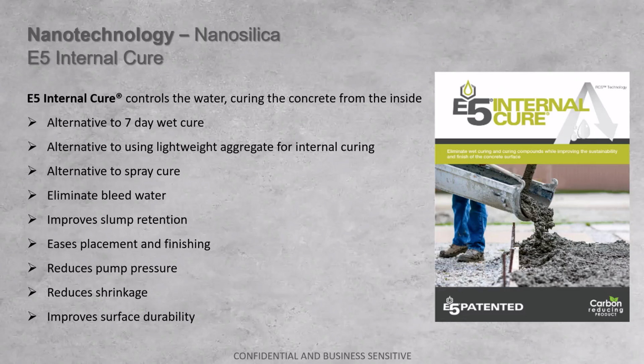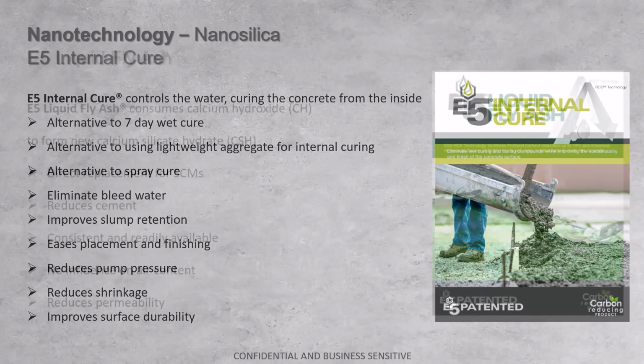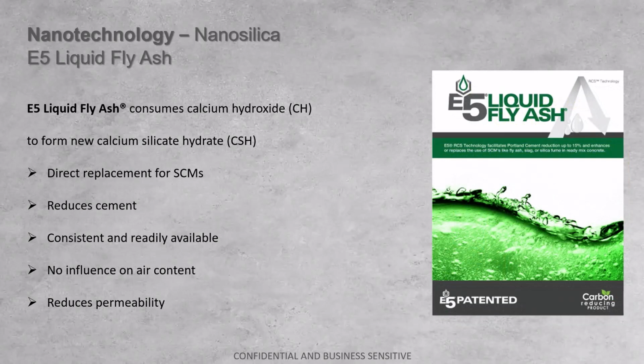We're saving water. And so this I-469 bridge project was the first opportunity when they were going to employ the E5 liquid fly ash product too. This is a liquid supplementary cementitious material that essentially consumes calcium hydroxide to form more calcium silicate hydrate. When you do that, you can use this product to optimize mixes. You can use it to lower cement content.